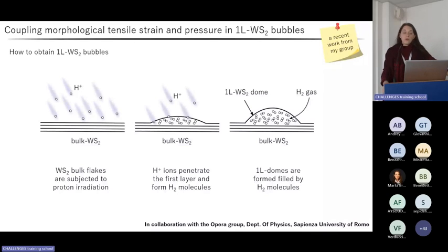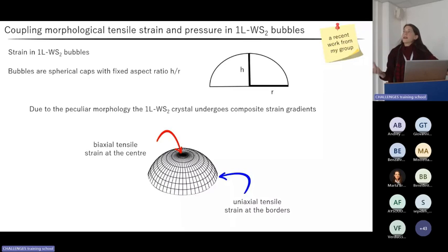From a geometrical point of view, bubbles can be thought of as spherical caps with a fixed aspect ratio. In the case of tungsten disulfide in particular, this aspect ratio is about 0.13, meaning that a bubble with a radius of 1-2 microns has a height of about 200 nanometers. Due to this peculiar morphology, the monolayer undergoes a perfectly biaxial tensile strain at the dome center, which progressively becomes uniaxial tensile approaching the borders.